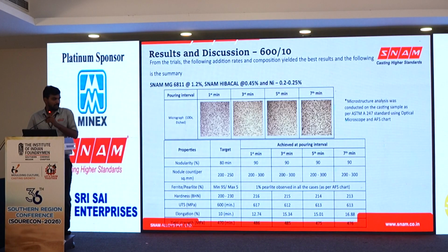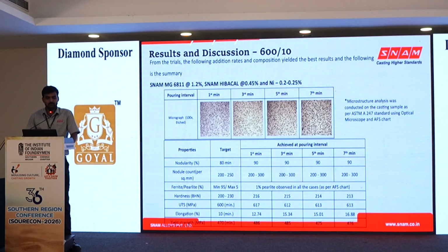So as per the discussed parameters, we have conducted trials by varying different compositions, and from the trials the following addition rates and composition yield the best results. The addition rates are as follows. We have used magnesium 6811 at 1.2% and inoculant Hibacal at 0.45% and nickel 0.2 to 0.25%. So the following table shows the metallurgical and mechanical properties of 600/10 grade at different pouring time intervals. So in the table we can see we have achieved nodularity almost 90% and nodule count as per the standard, and also we have achieved all mechanical properties as per the standard.